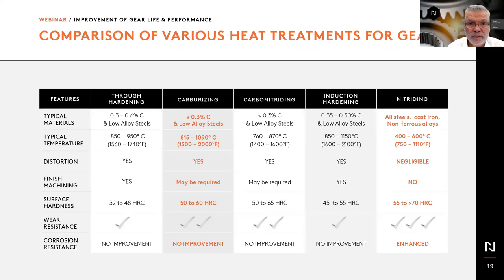So you can always expect some degree of distortion from carburizing, and in nitriding, on the other hand, there is a very negligible, if nonexistent, distortion. You may see some growth, also very negligible. However, no distortion if stress relief was done properly. So carburizing may and often requires finish machining, and nitriding usually does not. And there is no improvement overall for corrosion resistance in carburizing, whereas in nitriding, there is an improvement. However, really for gears, it's not usually what we are looking for.